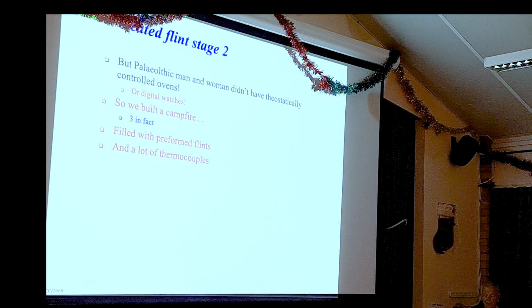So we had these fires, and what we did is fill them full of flint blanks, samples like this thing here. And then some of the flints we put under the fire, some in the middle of the fire, some on the top of the fire, and we filled the fire with thermocouples so we could monitor the temperature that's going on. And then we gave them all to the archaeologists and said, there you go, sort that lot out, what's good, what's not.